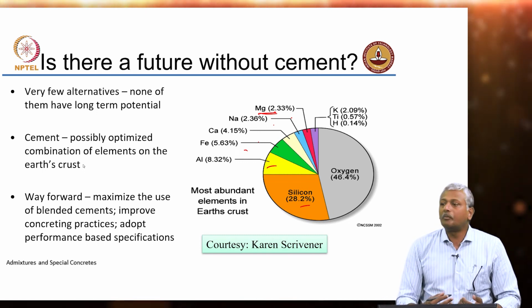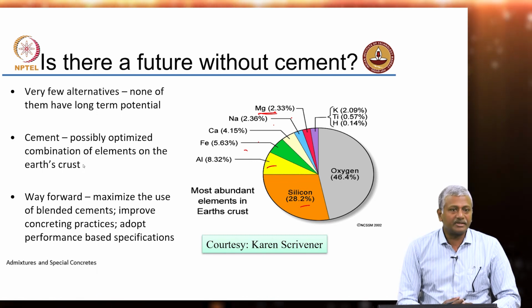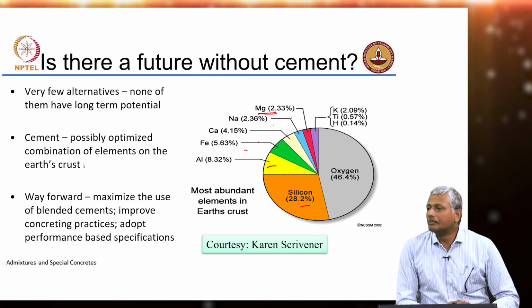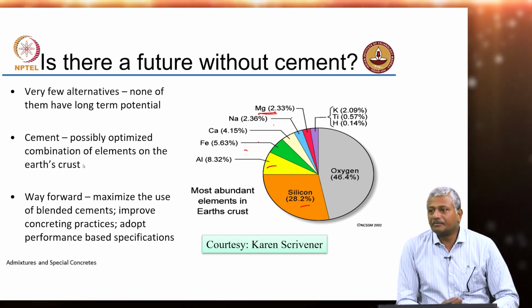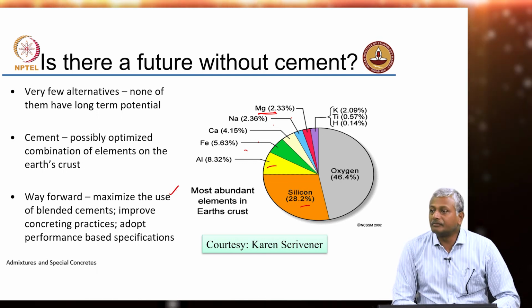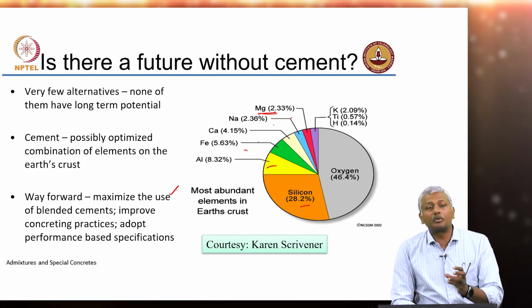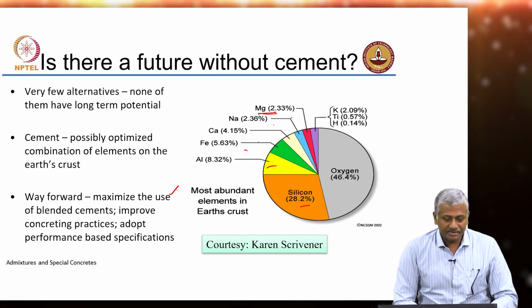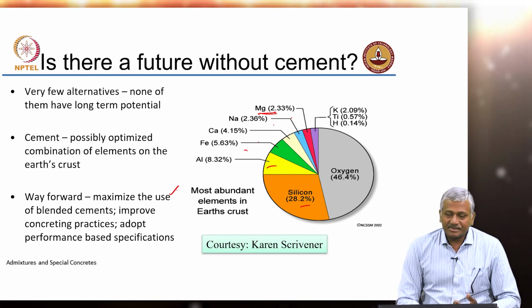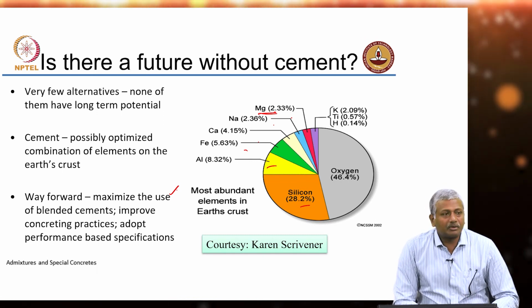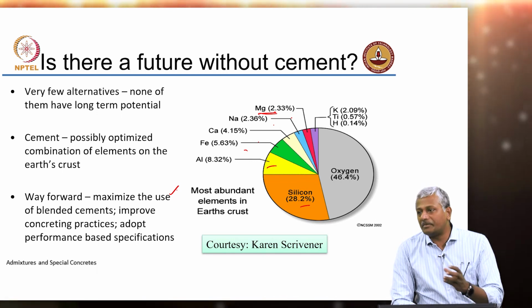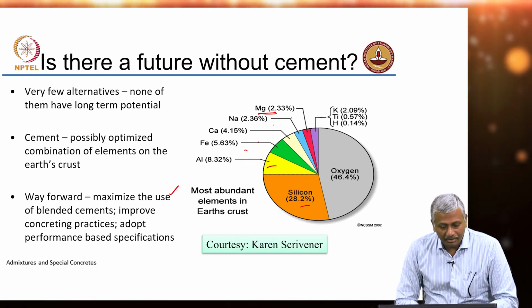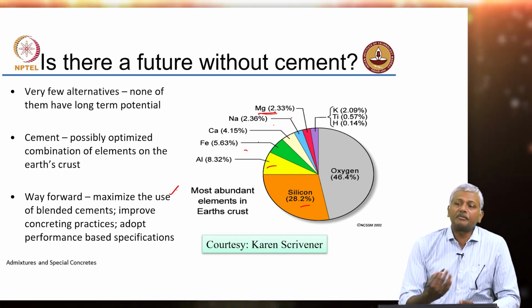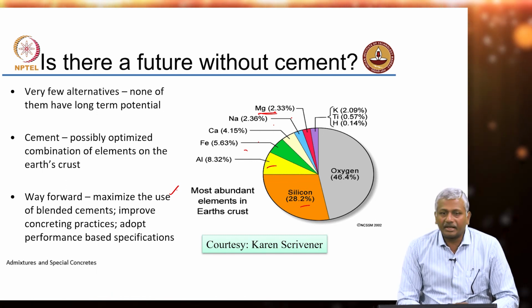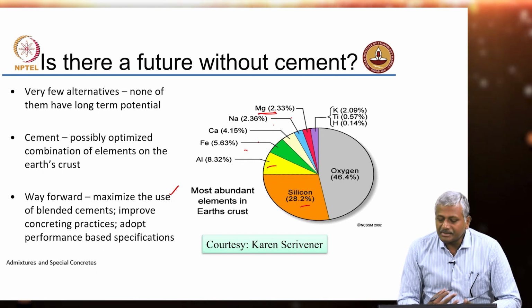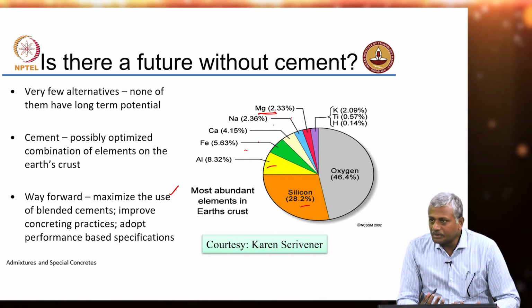So, the compounds that go into making cement are available in significant quantities. So, we can continue to produce cement and cement derivatives, but if we really want to make a major impact to the environment, then we have to start looking at how best to use blended cements which can reduce the quantity of cement clinker that is processed, that contributes a lot to your energy and CO2 in the concrete system. Improving concrete practices can also help to a large extent. We will see later when we discuss high performance concrete or special concretes that very often concreting practices can make a major difference, not just for high performance but also for ordinary concrete. And again, if you start looking at specifications that are performance based rather than prescriptive, you will again further save the extent of material that you actually use in your system. So, these are some strategies by which we can actually make do with the current cementitious materials.